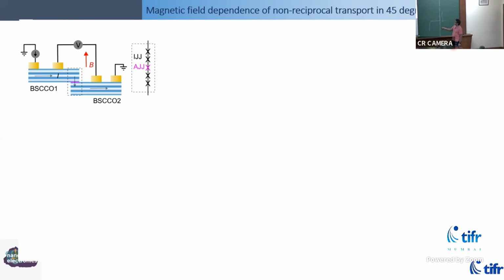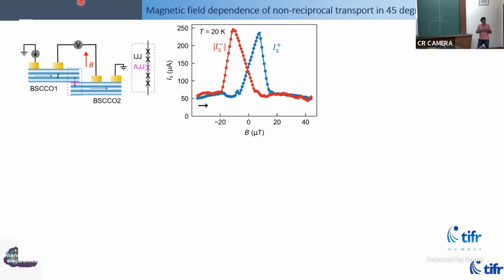So now the device looks like this, which is, I have one sheet of BSCCO and another sheet of BSCCO, and in the overlap region, the current has to go through in the C-axis, perpendicular, and that's the Josephson junction. And so we measured the switching current, which is the current at which the Josephson junction switches from superconducting state to normal state, with another knob, which will become relevant in a minute, which is magnetic field. If you notice this magnetic field scale, it's actually very, very small. Earth's magnetic field is comparable to this scale bar that I have on the x-axis. So we had to make a new kind of setup where we screen out Earth's magnetic field, and inside it, we made some homemade electromagnet to controllably apply these kinds of magnetic fields. Because the superconducting magnets have large enough trapped fields that you can't do these experiments easily.